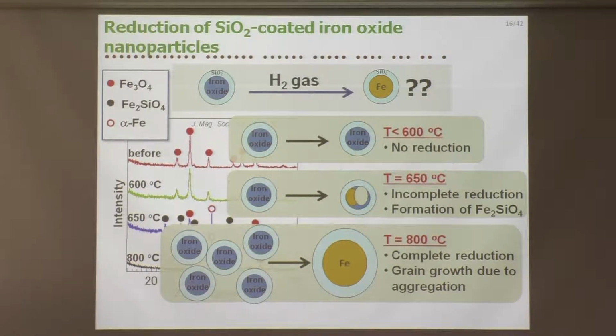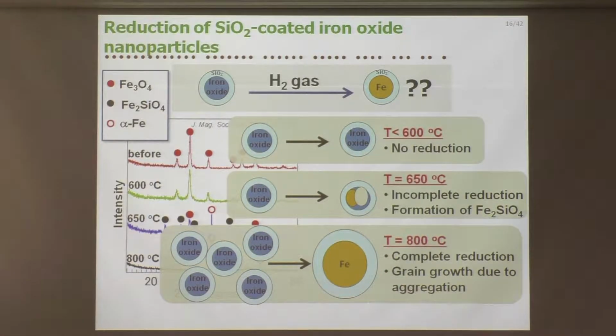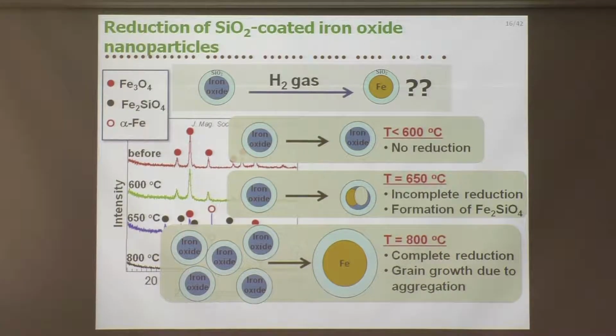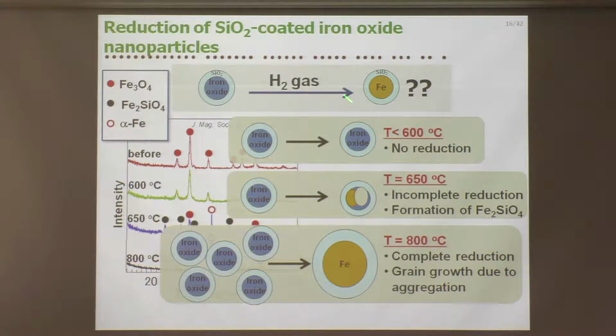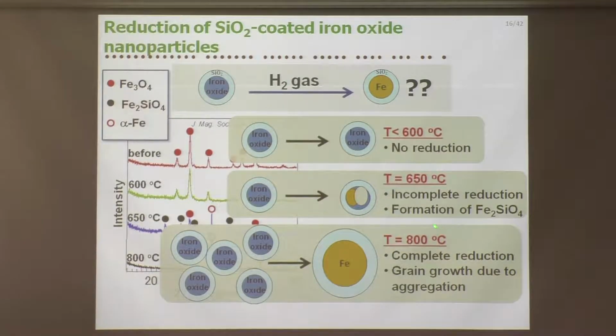Because of that, we want to get this kind of reduction style - I want to finish the reduction of the iron oxide nanoparticle just within the SiO₂ shell. However, if we use hydrogen gas, we have to carry out the reaction at 800 degrees Celsius, otherwise we cannot complete the reduction. But this temperature is too high to keep the isolated particle shape. That's a big problem - how to solve it?